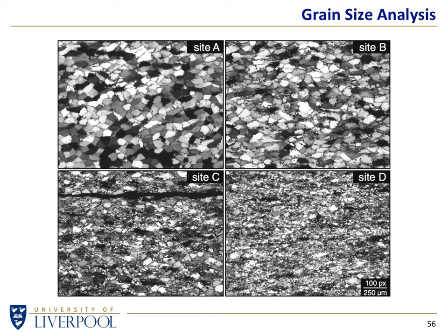And coming back to how that tells us about processes, here there's a sample of quartzite that's being processed by compression, and as time goes by, the compression is changing the grain structure of the sample. So it starts at A, and with higher compression, we've got a change of the grain structure. Higher compression still, we go to C, and higher still, we go to D. So again, your eye, I'm sure, is telling you that it's changing, and it looks like we're going from large grains to small grains.